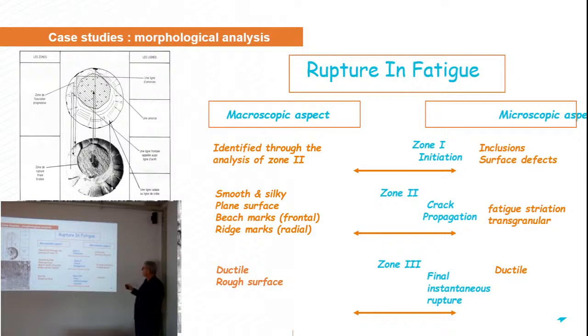From the microscopic point of view, if you analyze first the zone where the crack propagates, you can get fatigue striations. These are illustrated here, where you can see each striation corresponding to each fatigue cycle on the material. So this is very interesting to analyze what we call the interstriation distance. This gives some valuable information on the level of stress and the resistance of the material.